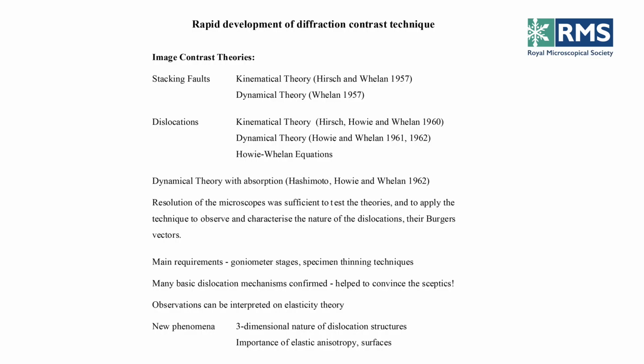And the next slide shows you this rapid development. The first thing was the stacking faults contrast, the kinematical theory, which both Mike Whelan and I developed independently, and then the dynamical theory of the contrast from stacking faults, which Mike developed, which was in fact the first dynamical theory interpretation of a fault in a crystalline material. And dynamical theory copes with multiple scattering, and kinematical theory doesn't. Yeah. In kinematical theory, you assume that there is no re-scattering of the diffracted beam into the direct beam, whereas a dynamical theory takes into account all the coupling between the diffracted beams and the incident beam.